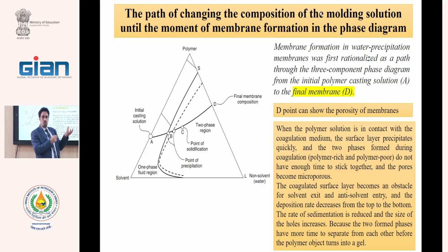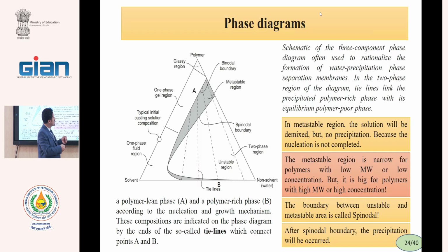When the solution is turbid but still liquid, we reach the binodal area, and when we add the final drop, after adding and mixing for 1 hour, the obtained solid is not redissolved, we reach the spinodal line. Therefore, for drawing of this diagram, maybe we need 2 months.